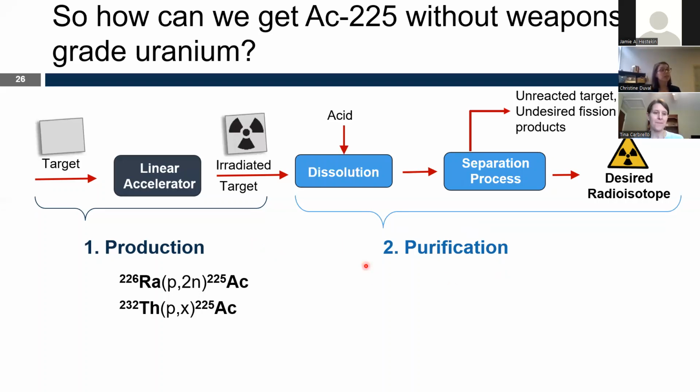The way that purification happens right now is through a series of resin-packed columns. That is the industry standard for most radiochemists. They're, like I had mentioned before, infinitely better than working with solvent extraction at the small scale, but we will see that we have a really large bottleneck associated with that purification process. The way it works is you would take a strong acid. And when I say strong, I mean something like 10 molar nitric or hydrochloric acid, sometimes a touch of HF for good measure, dissolve that target, and then it goes through the series of columns.